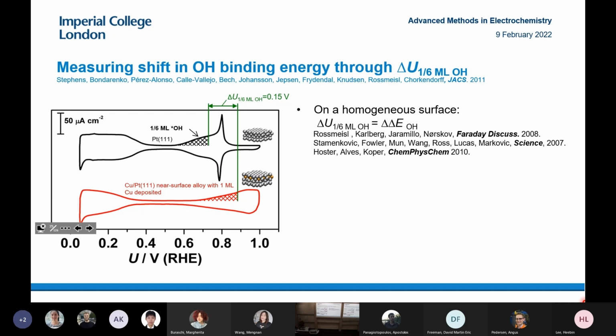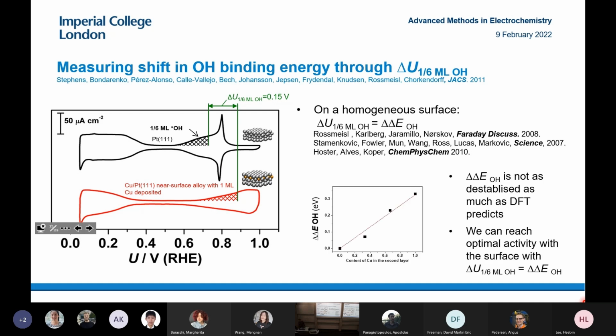So this is a surface we can directly compare to theoretical calculations. We think it was homogeneous because it's a single crystal surface. The theoretical calculations were done by Federico Calle-Vallejo. What he predicted is that as you increase the amount of copper, relative to platinum(111), we would destabilize OH. What I've shown here is when we put a full monolayer. So we expect that if we put less, we'd see less destabilization of OH. You can shift the binding energy by changing the amount of copper in the second surface layer through this ligand effect.